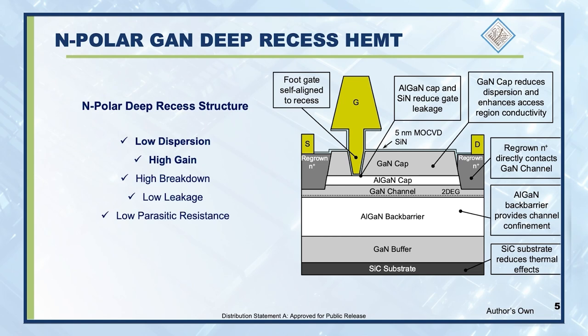And then finally, on top of the GaN channel, you have an aluminum gallium nitride cap and a gallium nitride cap. These are unique properties of nitrogen polar deep recess HEMTs. The gallium nitride cap reduces the dispersion, that is, dispersion being the difference in the performance between DC and RF of the device, and you don't want that dispersion to be high. In fact, you want it to be zero. In other words, whatever you see at low frequencies should be available at high frequencies.